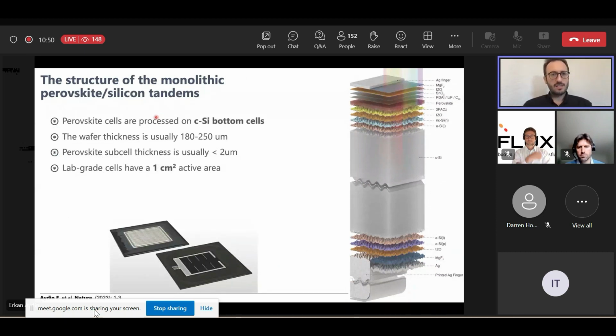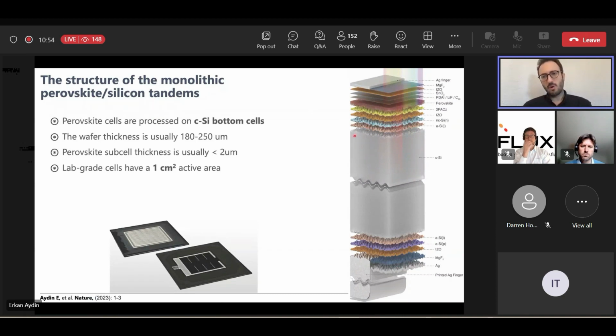Well, and how do these perovskite-silicon tandem solar cells look like? Basically, we have quite a thick silicon wafer, and I'm saying thick because compared to the perovskite, it's pretty thick. Today, the industrial wafers' thickness is usually around 150 to 180 micrometers, and for academic works, people mostly use 250 microns. And the total thickness of the perovskite layer is less than 2 microns. Imagine that we are just depositing nano layers on top of the crystalline silicon wafers, and we are forming the tandem cell. Here, crystalline silicon cells are absorbing the near-infrared light, as you see here, and the perovskite portion is mostly absorbing the blue spectrum, as I also showed on the solar spectrum a few slides before.